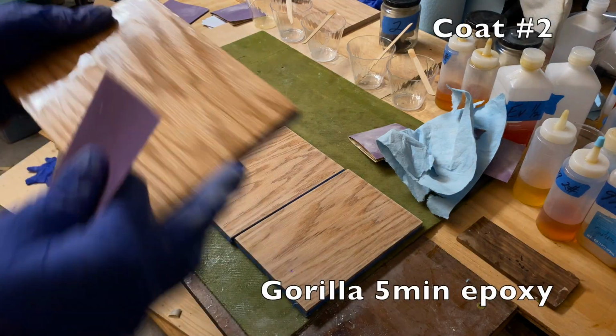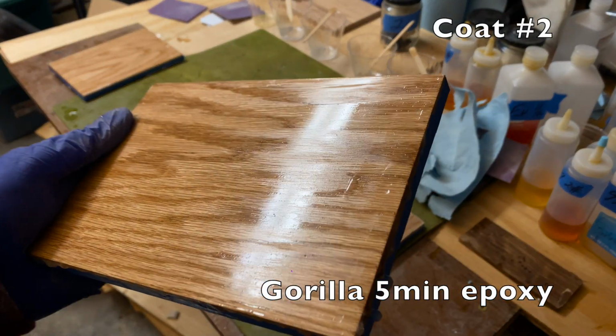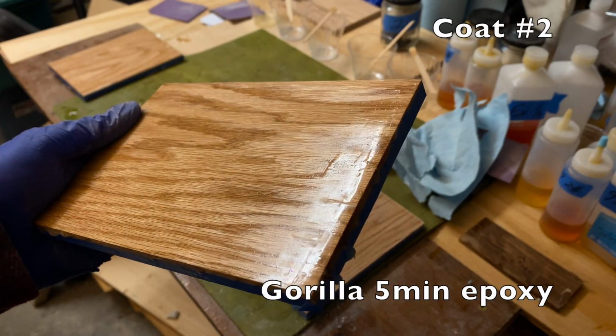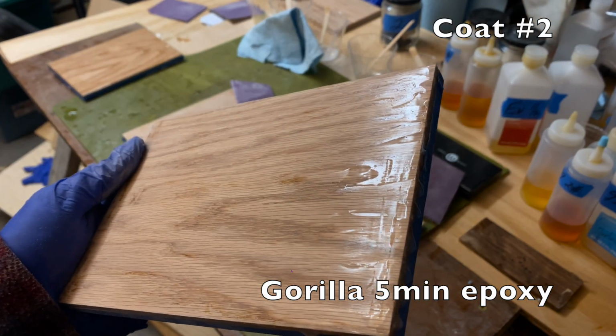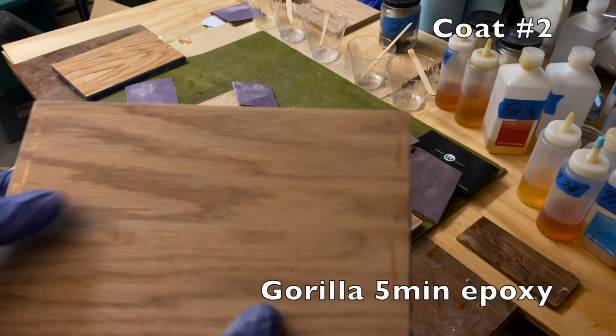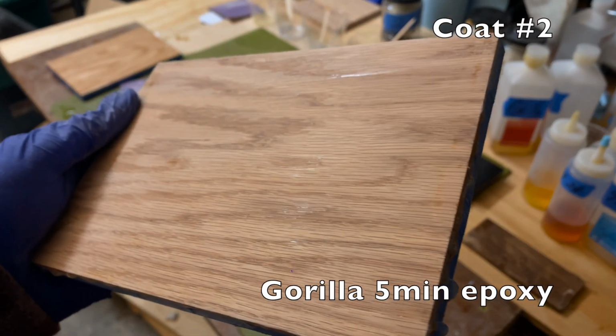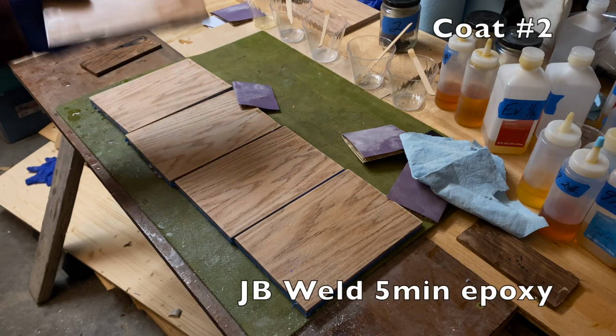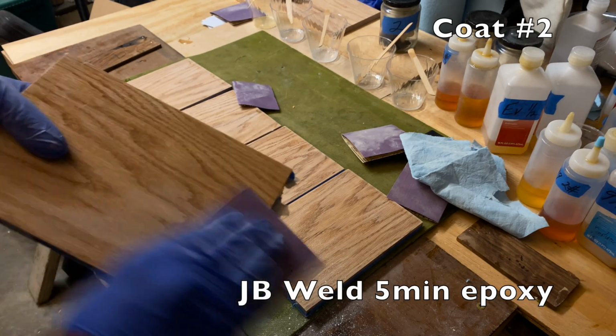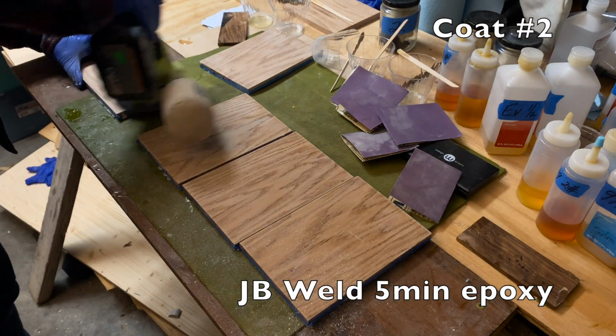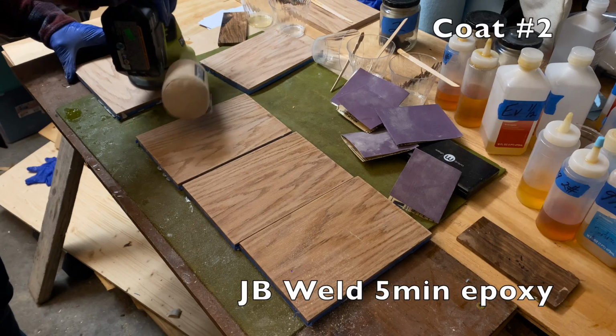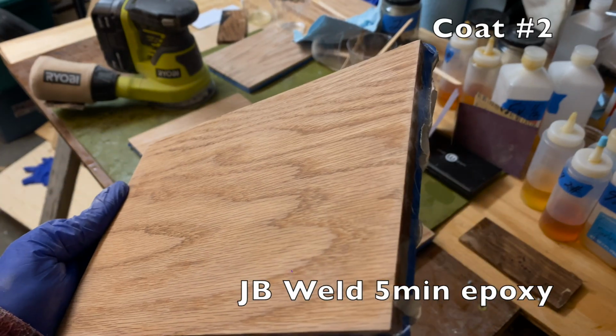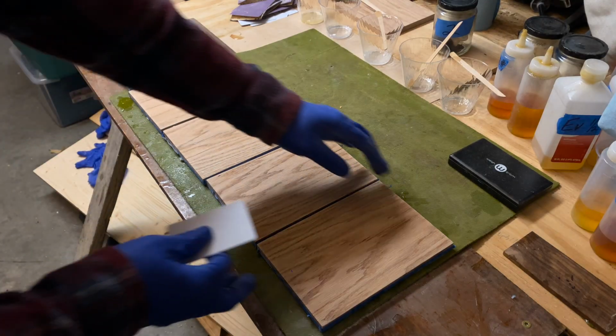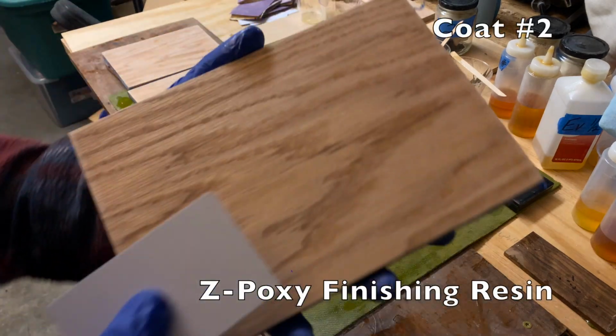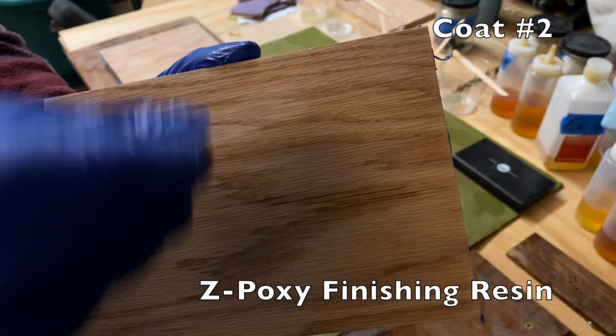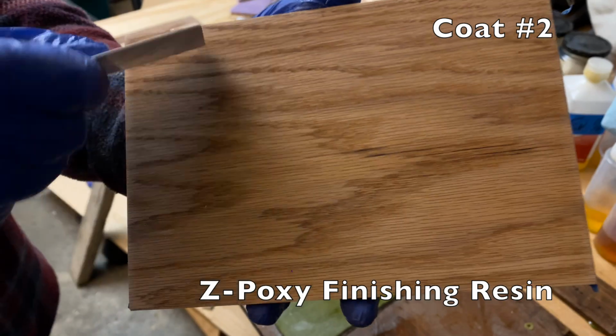I started out using the 320 grit sandpaper on the Gorilla Clear 5-minute epoxy, but after some hard sanding it still left quite a bit behind, and eventually I just used 220 grit and an orbital sander to finish up. And on the JB Weld Clear-Weld board, I just went straight for the 220, and in fact, I ended up going to the 220 on the orbital sander to finish this up as well. So I went back and cleaned everything up with the orbital sander and also with the 320 grit sandpaper, and I think we're ready for some finish.